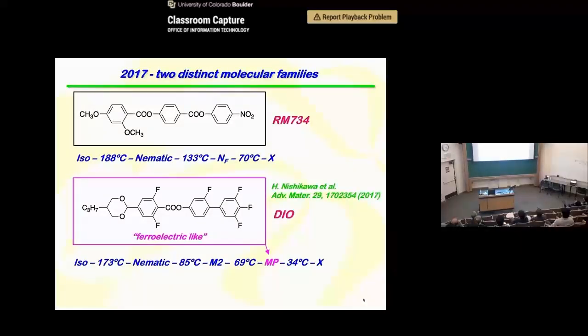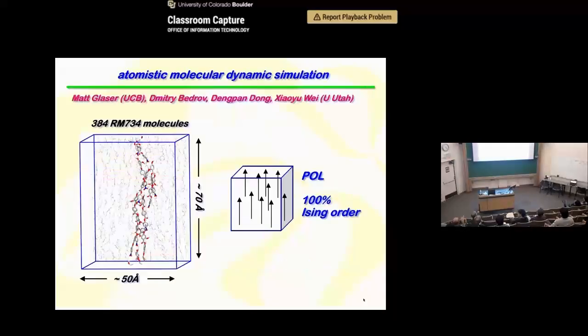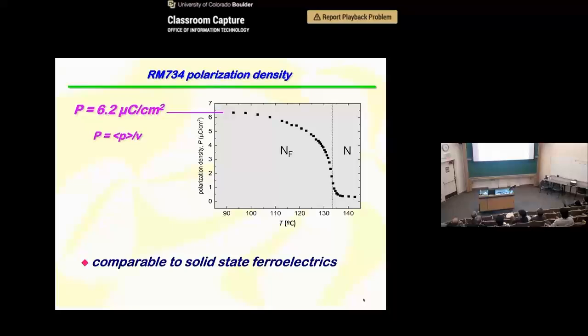Before you move on, the temperature-dependent plot that you showed seemed to have some polarization above the transition. Yeah, that's pre-transitional. When we looked in the video, you could see these lines starting, so their correlations grow in the nematic phase. So that's what's happening here. I mean, you have to put a field on to measure the polarization. You put a field on and you integrate the current. Yeah, this is fairly common.